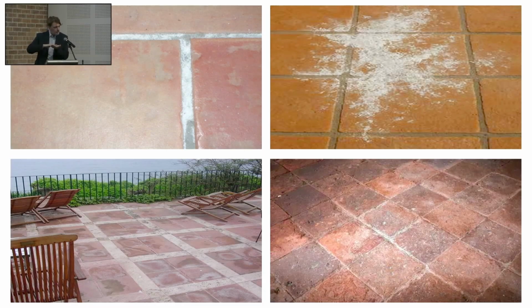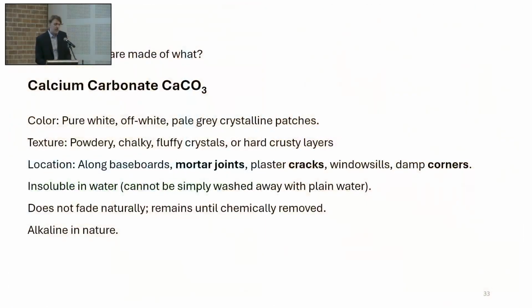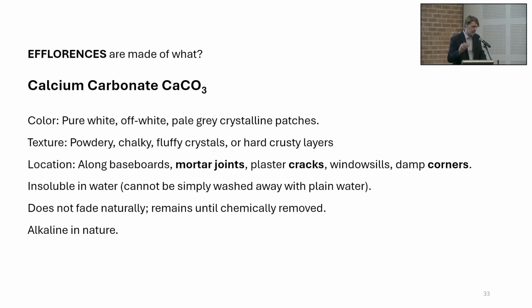By the time, it is consuming the surface. And this is a problem. You cannot solve it just by washing. I wash the surface and goodbye. Okay. So the first question we analyze in our study is, what is this white spot made of? Generally speaking, this white spot is made of calcium carbonate. Calcium carbonate is a white compound, crusty, a little powdery also, with a very high pH, that appears in the exit parts of the flooring or wall, so the joints, the cracks, the corners, the drainage, where there is water. It cannot easily be cleaned by water, as I told you before.